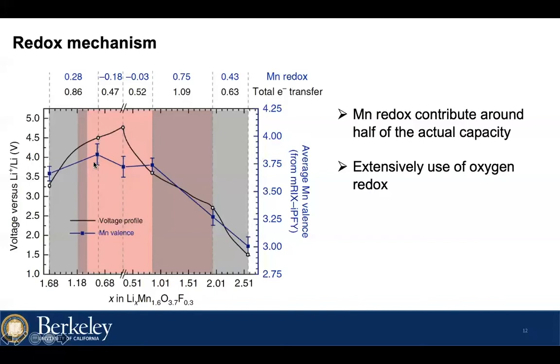After using up all the manganese redox, oxygen redox dominates at the high voltage region. During discharge, the oxygen gets reduced first, and the manganese valence remains constant. Then when the voltage gets lower, the manganese reduction starts to overlap with the oxygen redox. And at the low voltage region, the manganese redox again dominates.